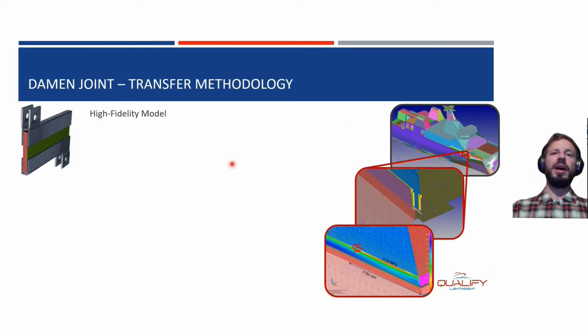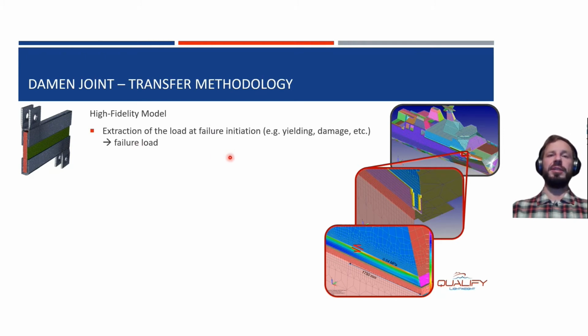Then we are now at the high fidelity models. We created the high fidelity models. What we do with that one is extract the load at failure initiation. In the current approach, we consider large-scale yielding of the adhesive or the steel as failure initiation. We can consider damage of the interface or the composite failure initiation criteria. We look at when the first criterion takes effect, and then we track the load for that one. We save the load. We note the failure load.